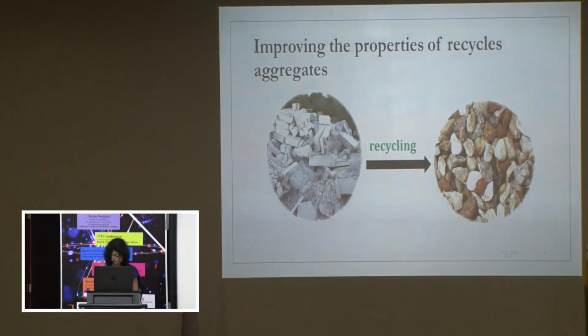The major drawbacks that hinder the use of recycled aggregates in structural concrete are found to be the porous attached mortar on the surface of recycled coarse aggregates and the micro cracks formed on the surface of recycled aggregates during the manufacturing process. The porous surface of recycled aggregates increases the water absorption capacity drastically. The workability of concrete made with recycled aggregates consequently will vary due to its high water absorption. Due to high porosity of recycled aggregates, the interfacial transition zone, that is ITZ, between the new cement paste and recycled aggregate becomes very porous and weak, leading to low strength gain in concrete.